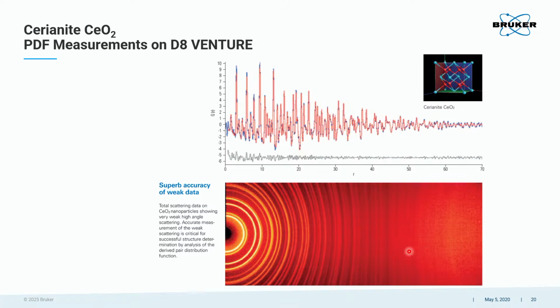PDF. With the detectors now being photon counting, and with really strong X-ray sources, the geometry is right that we can collect data to very high resolution. PDF analysis is now very doable on single crystal instruments. We also don't need the high resolution you traditionally strive for in XRD experiments. So this is a good example where we can creep into the XRD domain, where we have some advantage in collecting really good data. And as I said, there is a lot of interest from the battery folks.